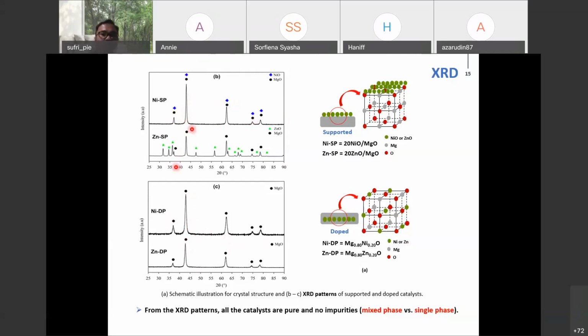Another characteristic from the XRD pattern: the supported catalyst appears as a mixed phase, more than one phase, because the active metal is outside. So supposedly it appears in mixed phase. For this nickel SP, the nickel oxide and magnesium oxide XRD peaks coincide and overlap each other, because the crystal structures of nickel oxide and magnesium oxide are similar. It is a cubic crystal structure. This is why they coincide.